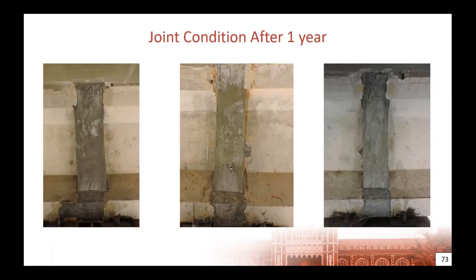So this was done in 2019, and we've been able to monitor it throughout time. These were the joints about a year after. And this center joint is the joint that had the issue with the formwork, pulling water from the UHPC and taking some of the material with it. And as you can see, it more or less looks the same.